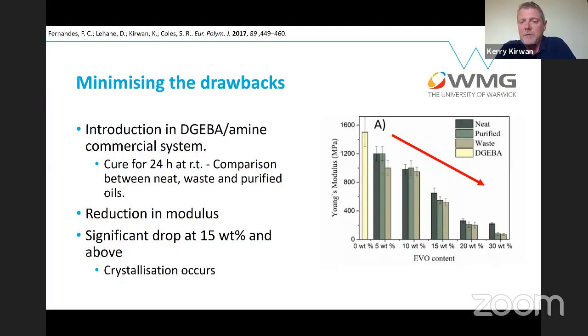And you can see that, as you might expect, it doesn't perform quite as well when you look at the Young's modulus, strength and stiffness. But below 15% actually it wasn't too bad. Above 15%, you ended up with a significant drop off, and you ended up with crystallization and these rather disparate regions within the composite and the polymer of the two different materials. But we did learn a lot from this, and one of the things we were interested in is whether it would act as a plasticizer and an impact modifier.